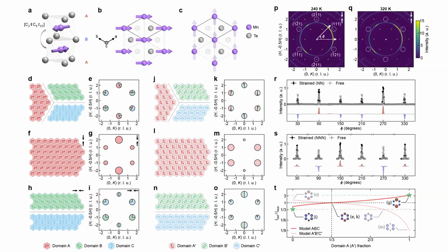Well, in principle, if the band is split, right, you should expect to see the chiral splitting in the spin waves, but that's never been seen, at least not in manganese telluride. It's been seen in insulators, but this is a fairly large challenge experimentally, mostly because you first have to detwin it, because once it becomes twinned, then it's mixed, right? And then you have to put it in the polarized neutron beam, which is quite hard. Yeah.